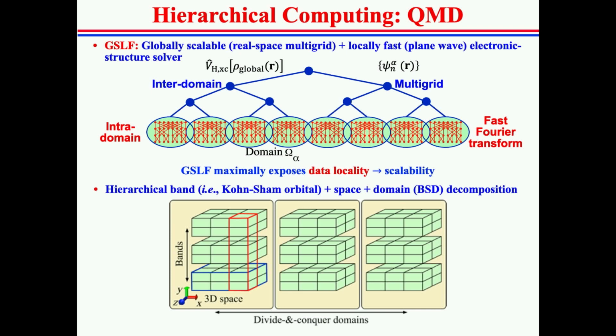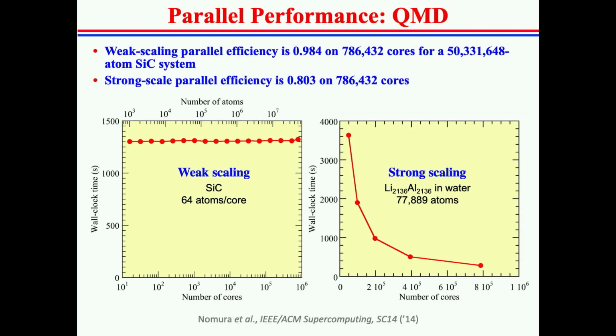On a parallel computer, we divide the computation into domains, so domain decomposition. Then for higher parallelism, within each domain, we combine band decomposition to split the quantum wave functions among processors, and also spatial decomposition, a kind of hybrid parallelization. This is a little bit old data, but we achieve over 98% of the perfect speedup in a weak scaling setting for a 50 million atom system on 800,000 cores. We also get reasonable strong scaling parallel efficiency for a much, much smaller system, like 80,000 atoms instead of 50 million atoms. So that's quantum molecular dynamics.